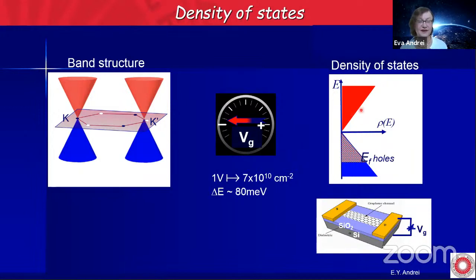Here in graphene, because of this linear dispersion, 1 volt of gate voltage buys you about 7 times 10 to the 10th carriers per centimeter squared, or it moves the Fermi energy by 80 millielectronvolts, which is a huge amount. In terms of temperature energy scale, it's about 800 degrees Kelvin.